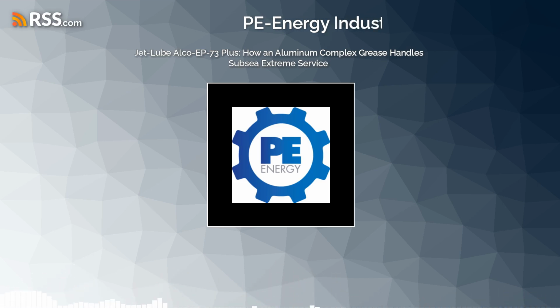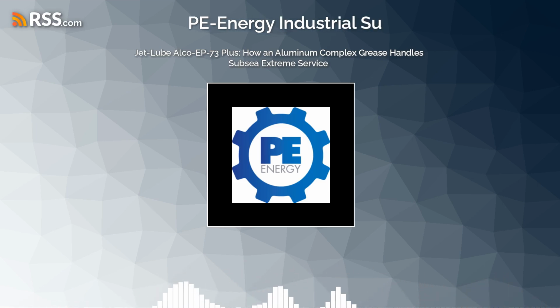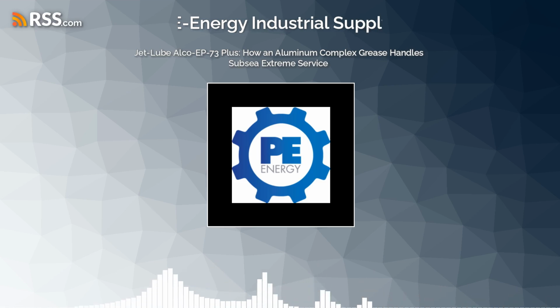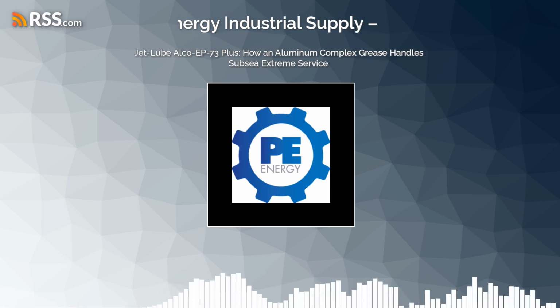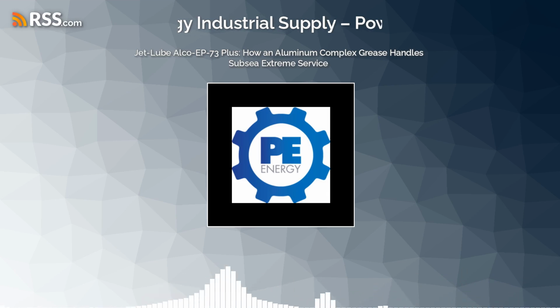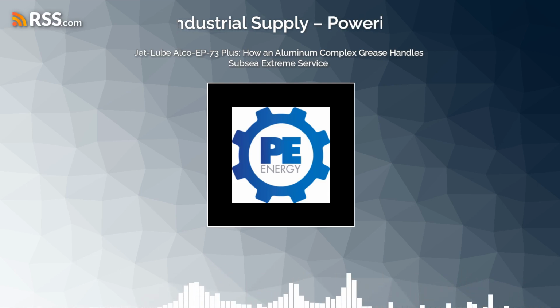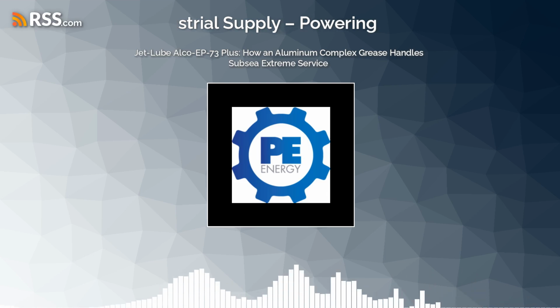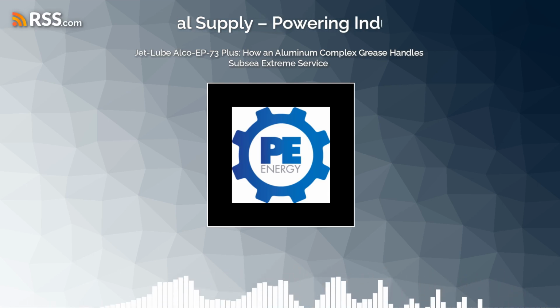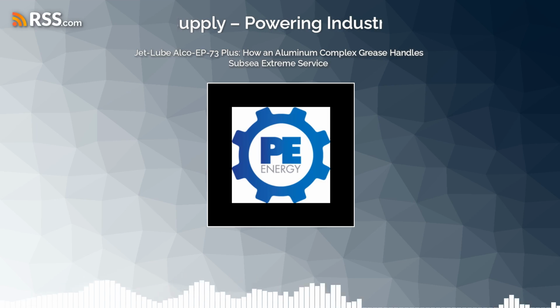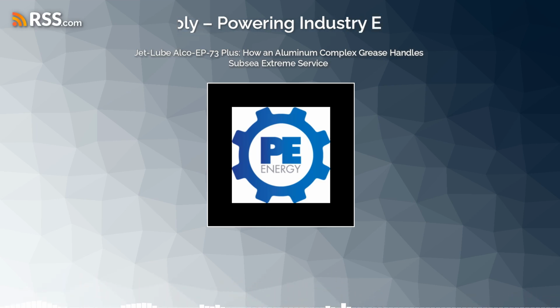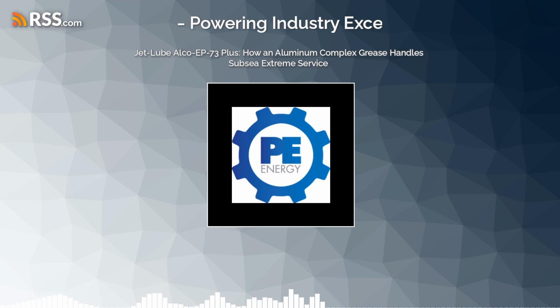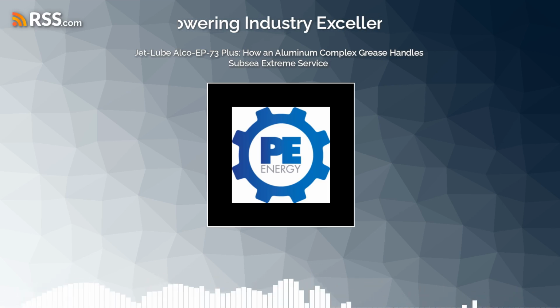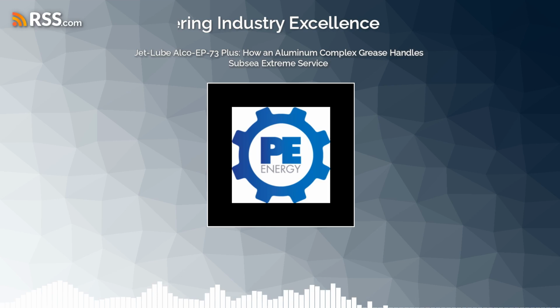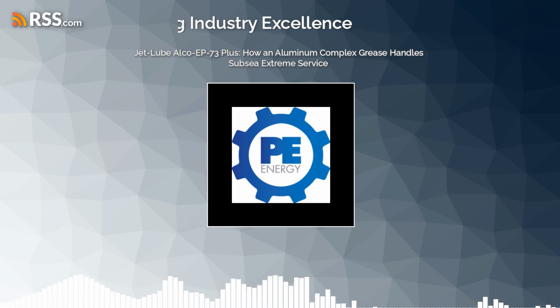A very advanced system. It's an aluminum lattice suspending carefully measured oil, reinforced with hydrophobic polymers, and shielded by non-plating organics. It's designed to survive 500-degree heat, extreme subsea saltwater exposure, and the kind of microscopic, localized pressure that would literally weld lesser metals together. It forces you to rethink how you view industrial maintenance entirely, doesn't it? It really does. We look at massive steel rigs and marvel at the mechanical engineering. But the mechanical engineering only functions because of the chemical engineering hiding in plain sight, contained within a red paste.